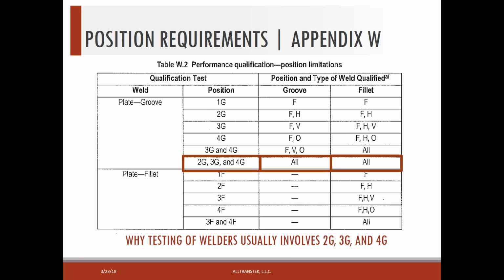So when you go into any of the codes, they're going to list each position that you take, which we just talked about, and they're going to show you an associated position that you're qualified in. So if you take a 1G test, you're going to be qualified for flat, which would be 1G. Appendix W lists a little bit different than D15-1, but the F under groove would be 1G, and then the F under fillet would be 1F.